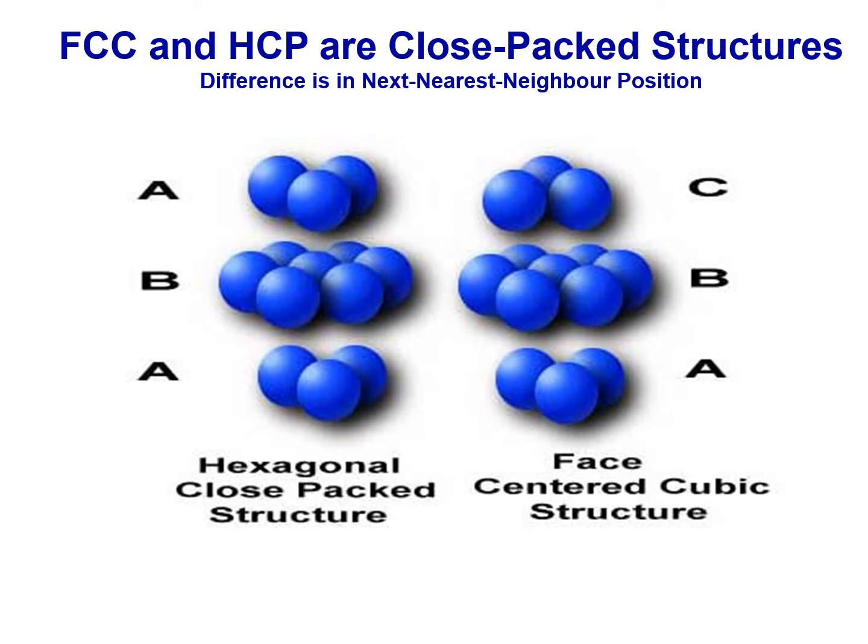And that's all it takes to change the crystal structure radically from a hexagonal to a face-centered cubic. This is also important when it comes to transformations, because it's very easy to transform from this hexagonal close-packed structure to a face-centered cubic structure. You simply have to take one layer and slide it a little bit.